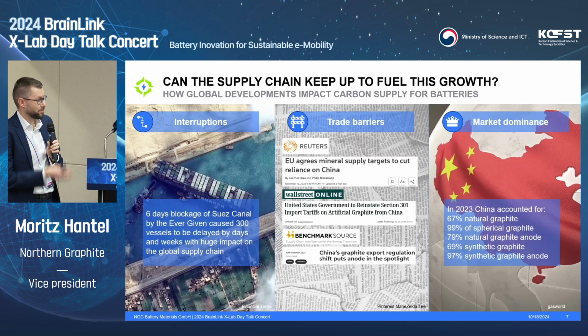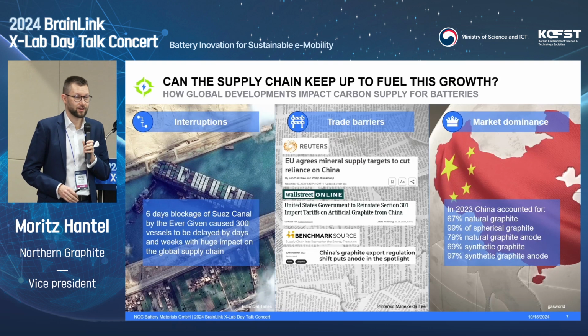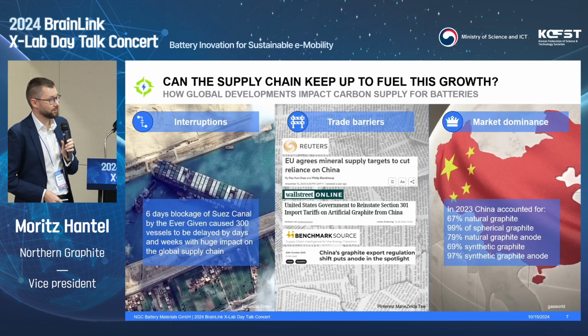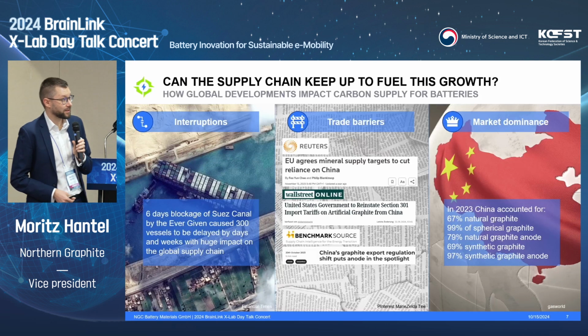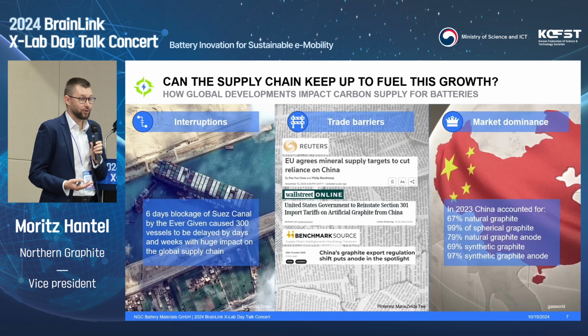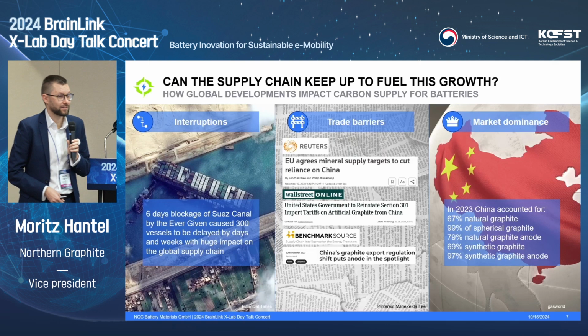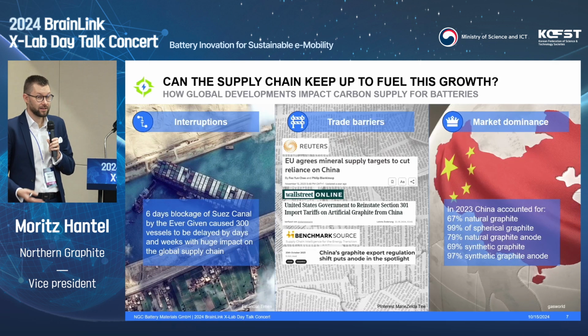And then for sure we have the market dominance of China. That's the reason why China is mentioned so many times in the news. In 2023, about 70% of graphite was mined in China. 99% of the spherical graphite, which is a precursor for natural AAM, came out of China. 80% of the anode active material on a natural graphite basis came out of China. And on the synthetic side we have 70 and 97%. So in the end, without China at the moment, there is no anode. Without anode, there is no battery.